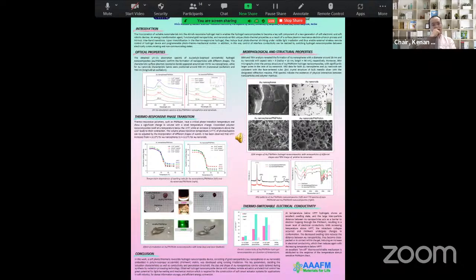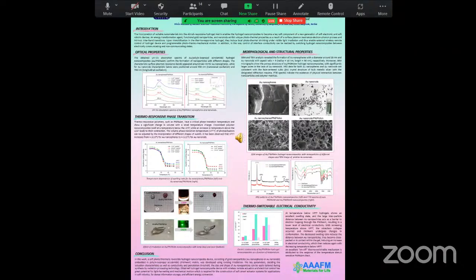The obtained results show that the volume phase transition temperature of photoactuators can be adjusted by incorporation of different shapes of gold nanoparticles. It has been observed that the VPTT increased from gold nanospheres to gold nanorods. Moreover, we tested the photothermal shrinking under visible light irradiation. We used a lamp and a laser, and a more pronounced photothermal effect was observed in the case of nanorods. Under laser radiation, the sample with nanorods shows the conversion of optical to mechanical energy, confirmed by clearly visible bending of the hydrogel nanocomposite.